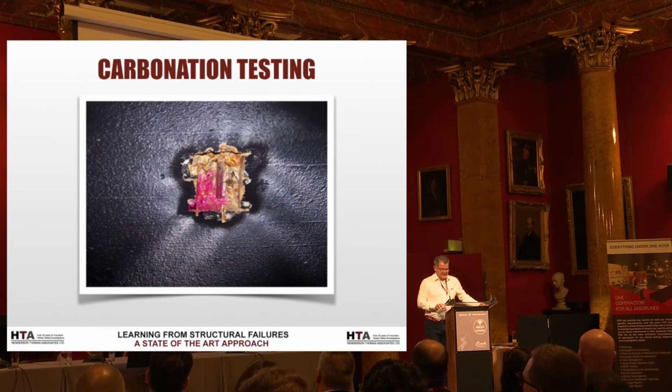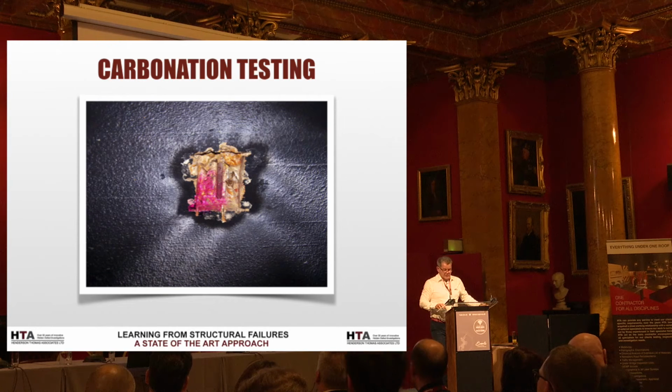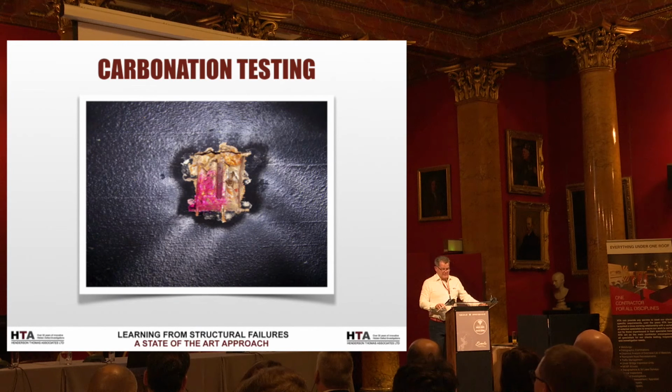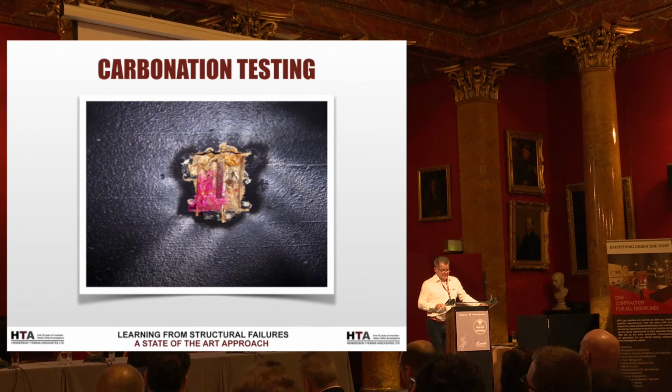More importantly is another technique or method that can actually cause corrosion to reinforcing bars. Concrete, by its nature, is an alkaline environment. I don't need to tell most of you here that. That alkalinity produces a passive film around the reinforcing bar, which protects it. And as long as oxygen and water and that protective alkalinity are not changed, the bar should stand in good stead for a number of years.